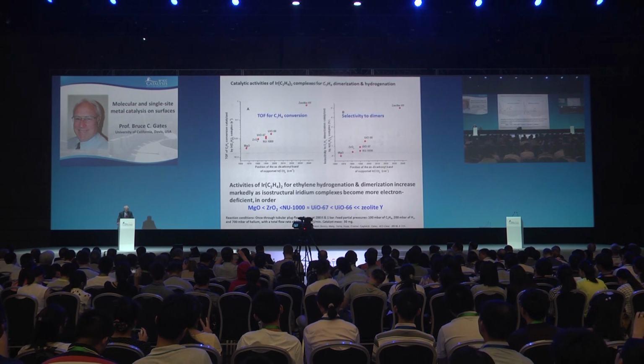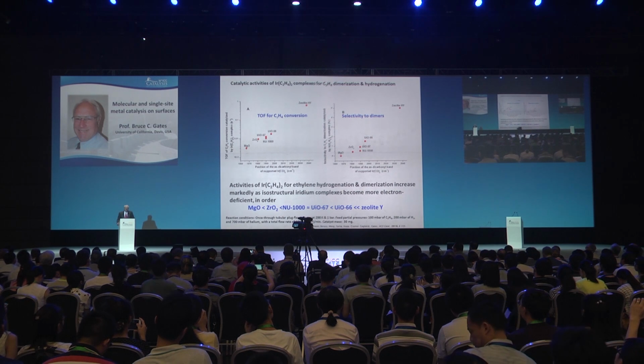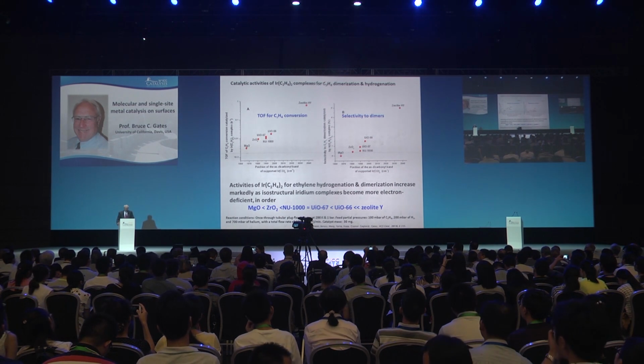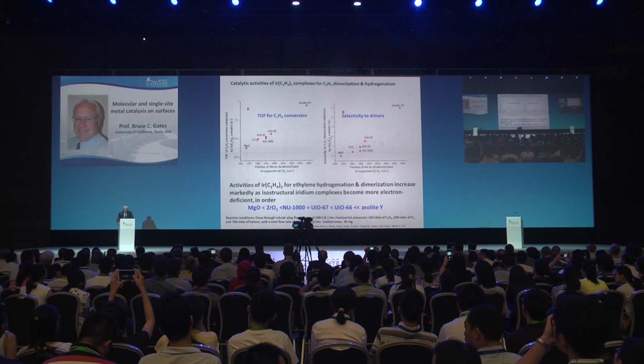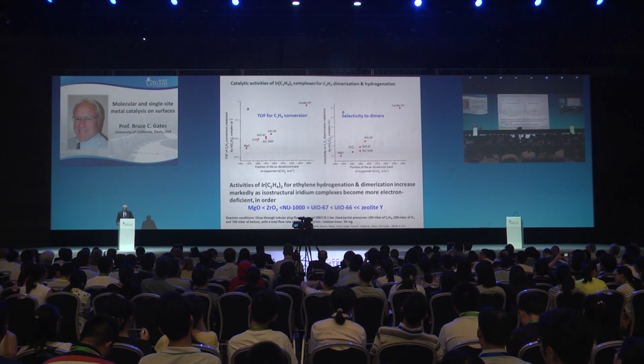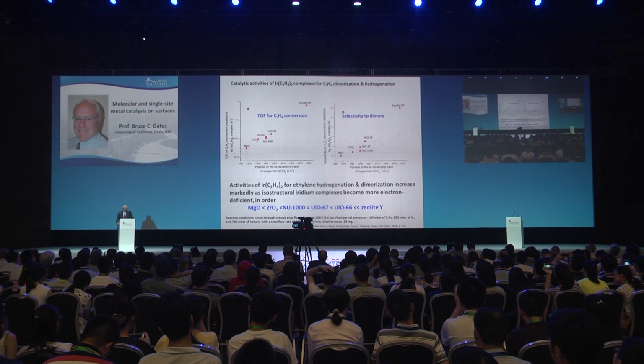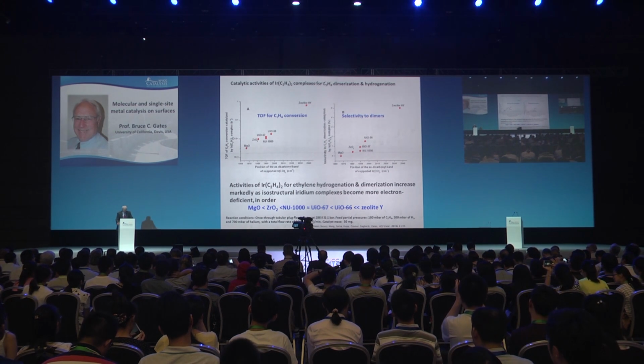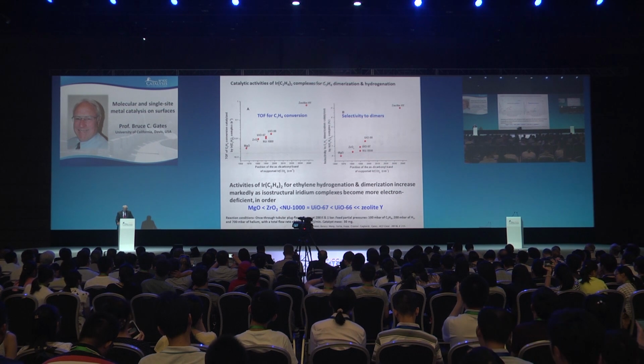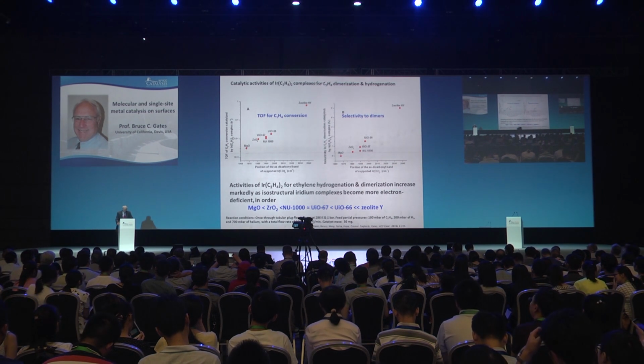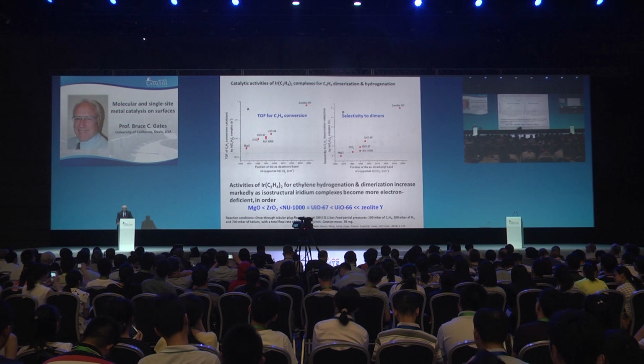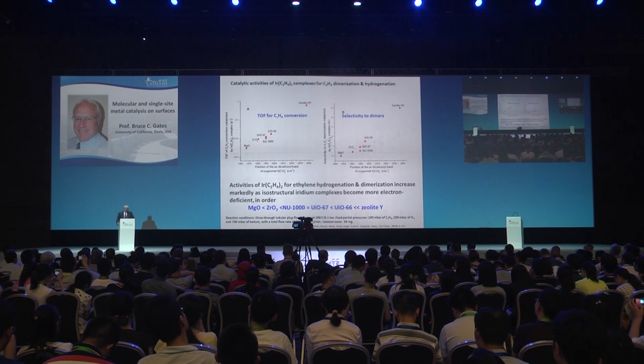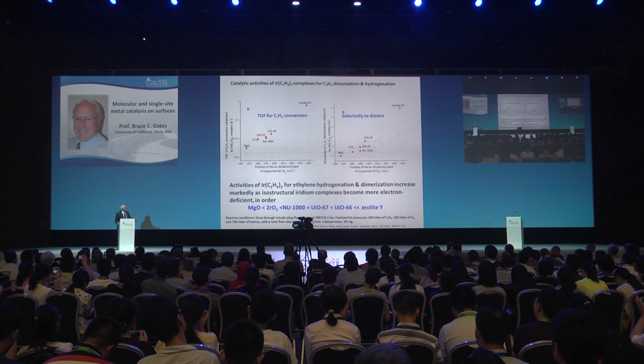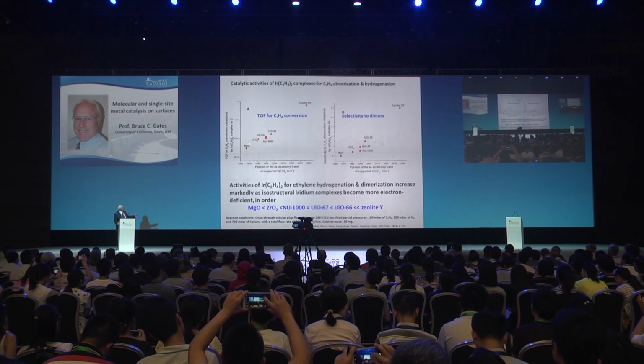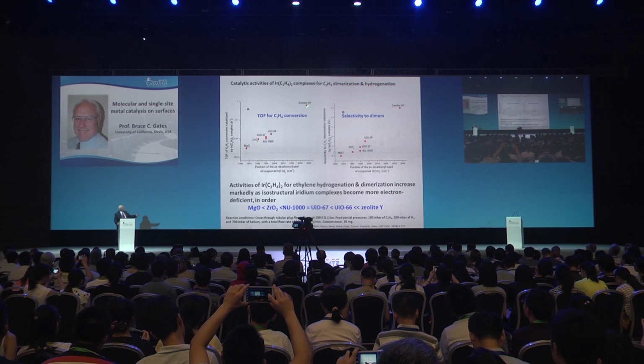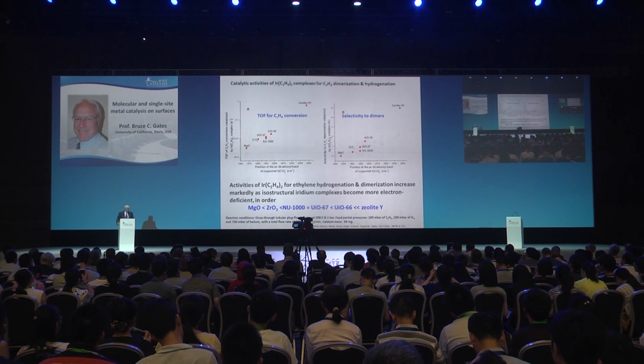Let's go back to the question of the effect of the support as an electron donor ligand. So a measure of that is the frequency of the asymmetric and symmetric CO stretches in the spectrum, and I pointed that out in an earlier slide. One has a nice correlation over orders of magnitude between the turnover frequency for ethylene conversion and that measure of electron donor tendency. So the electron donating support's not a very active catalyst, and the one that's electron withdrawing really is a much better catalyst.